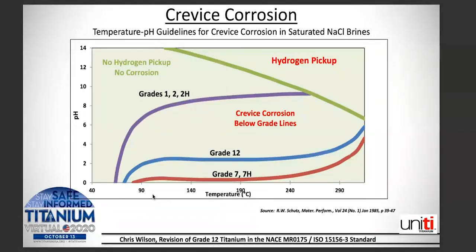On this slide, you can see the crevice corrosion chart that many of you are probably familiar with for titanium alloys. This is crevice corrosion in saturated sodium chloride brines. As you can see, there are different lines for the different grades of titanium. The standard available grade 2, grade 1, grade 2H.